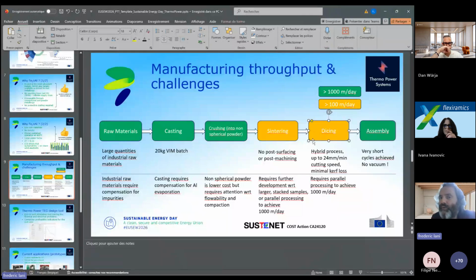Because when you manufacture small thermoelectric legs of, let's say, 1.5 millimeters by 1.5 by 2 millimeters, or even smaller than that, if you lose half of the material, it's really bad. So we really minimize kerf loss here with the hybrid process. Here with dicing, there is no solution.